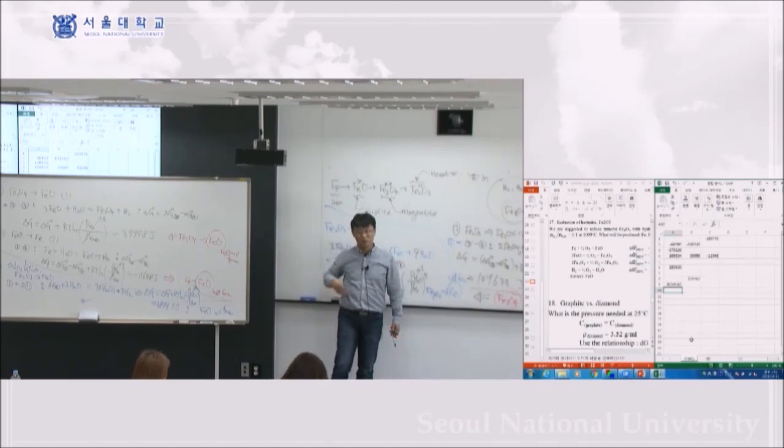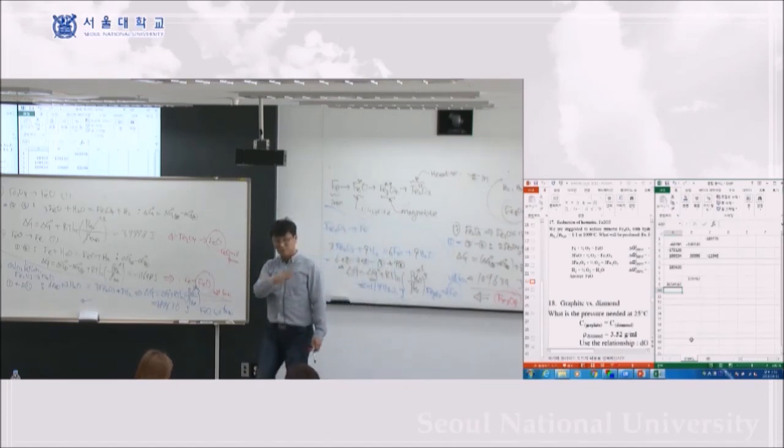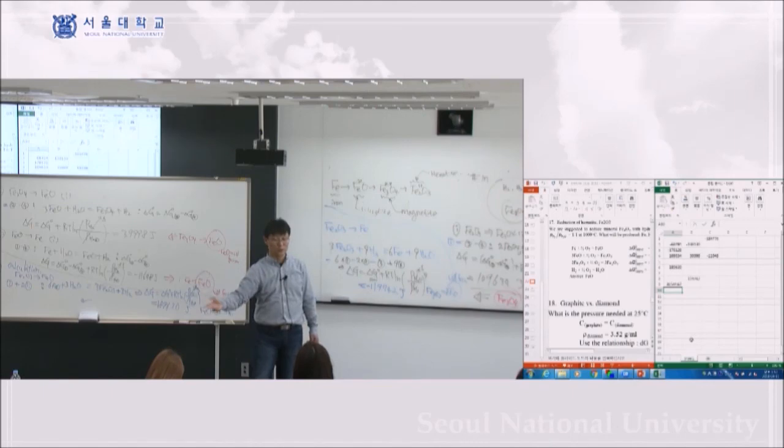Okay? So the easiest way is you start from the first material you have in the question, and then you do the calculation for the second one, and then okay, the second one will form or not. If it's not formed, forget about it, and you start from the original one, and then test the other one. Is it formed? Okay, it's formed. Okay, then let's take that one as the new starting material, and then check with the other one. Is it going to form or not? So you have to go step by step with all the possible intermediate phases. That's the safest way, the shortest way actually. Otherwise, you have to do all this, and then think about, okay, between these you have to do it again and again.